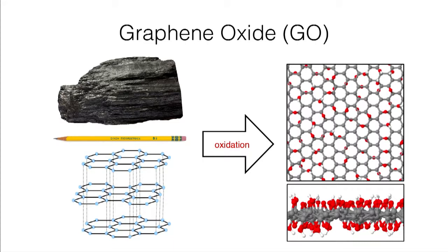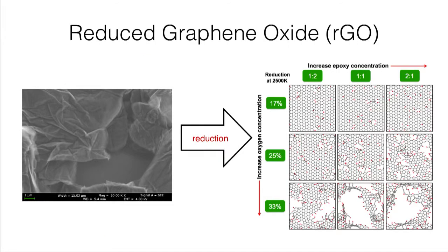And so we've taken a hint from the electronics industry and reduced the graphene such that we can remove some of those oxygen groups, which also removes some of the carbon lattice and creates defects. The electronics industry doesn't like those defects because, again, it reduces conductivity. But those defects, which we think from our computational studies that we can control reliably and scalably, are the pores that we're creating in our material.